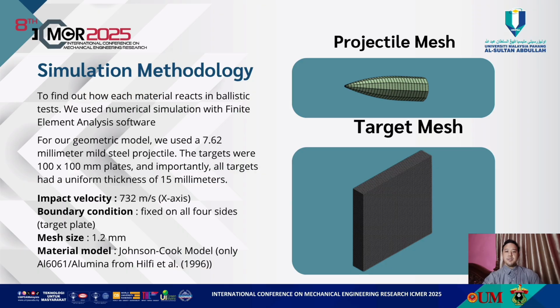For our geometric model, we use a 7.62 mm mild steel projectile. The targets were 100 by 100 mm plates, and importantly, all targets had a uniform thickness of 15 mm. This allows us to test the absolute performance of each material within the same volume.